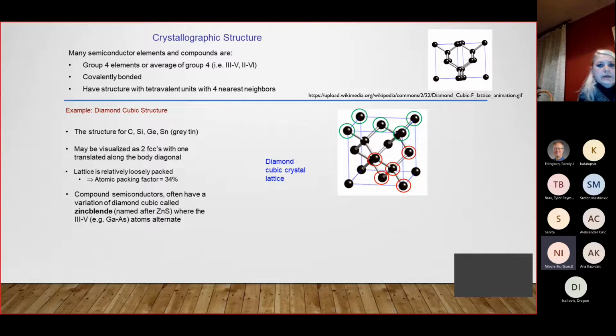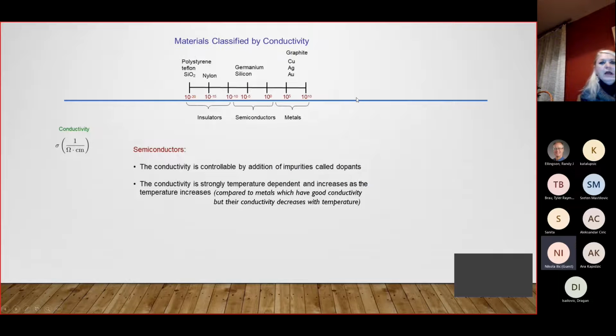Lattice, then this lattice is relatively closely packed. Atomic packing factor is somewhere around 34%. And compound semiconductors often have a variation of the diamond cubic called zinc blende, named after zinc sulfide, where, for instance, III-V gallium arsenide atoms alternate. So you can have here, for instance, gallium, and on the other place you can have arsenic.